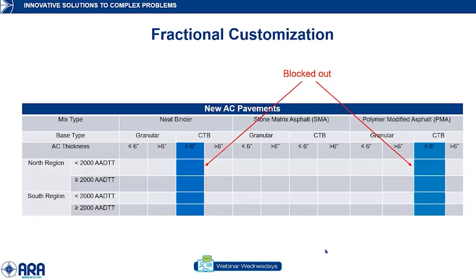Turns out that you don't have hardly any pavements using the neat or polymer modified asphalts where you use the cement treated base under a pavement that's 6 inches or less. So the nice thing here is that it's easy to physically block those out and then not include them in the analysis and then try to fill the remaining cells. So that's the reason for this primary versus secondary tier setup, which has two purposes.